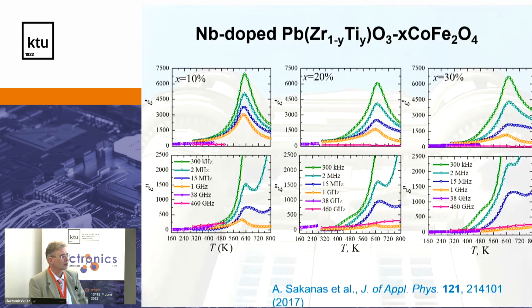material, which is called artificial multiferroic, where you take PZT, which is a ferroelectric and piezoelectric material, and cobalt ferrite, which is a magnetic material. So the idea is to combine magnetic and ferroelectric material to have a multiferroic, where you can switch the polarization with an external magnetic field and the magnetization to switch with an external electric field. So that's for memory devices, for example, and similar stuff. So the different concentration X shows the cobalt ferrite, and we see lead zirconium titanate, PZT, has a phase transition, a nice anomaly, which is clearly expressed, but we do not see anomalies or contribution of cobalt ferrite. So what to do?